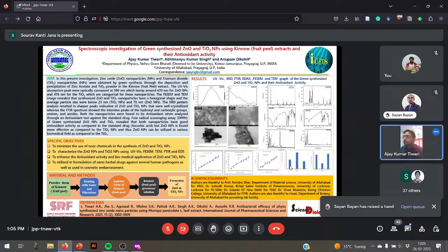The antioxidant reducing power, ARP value, of the titanium dioxide nanoparticle and zinc oxide nanoparticle were found lesser as compared to the standard drug, ascorbic acid, which indicates that they have a more antioxidant activity. The ARP value of zinc oxide nanoparticle is more than the titanium dioxide nanoparticle, which indicates that the zinc oxide nanoparticle is more antioxidant as compared to the titanium dioxide nanoparticle. Thus, titanium dioxide nanoparticle and zinc oxide nanoparticle, both synthesized from the Kinnow fruit peel, can be utilized in nanoherbal drug and preparation of the antioxidant.